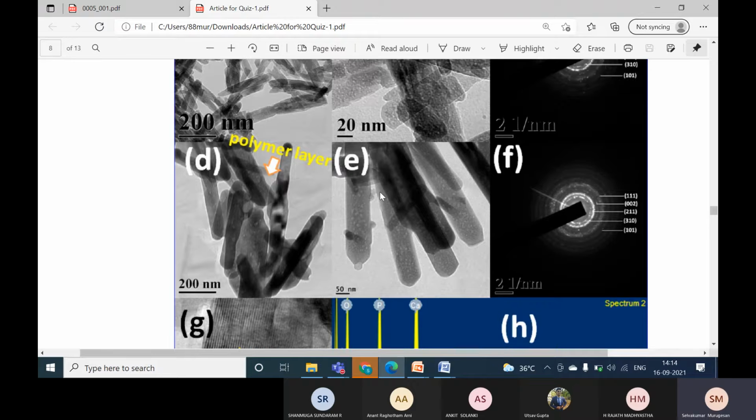And the other mechanism I was discussing with you guys is bubble formation. With the help of the pulsed method, like 2 seconds on and 1 second off, you can play around with the heat transport and heat transfer issues. Once the bubbles form, the moment you switch off the ultrasonic probe for that 1 second, the bubbles will break, and those voids will be present in your nanomaterials or nanorods. Okay.